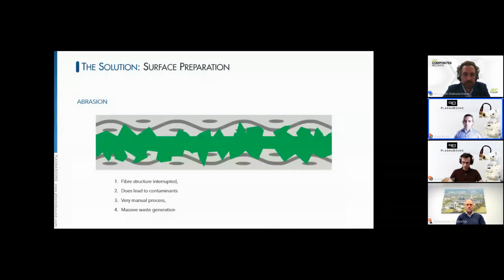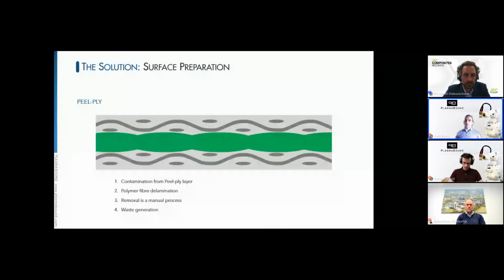Then finally, we have peel ply. It's very effective when done right, and many specialist adhesives are formulated to match it, specific sheet-based adhesives. However, contaminants from the peel ply layer and moisture ingress are not uncommon, particularly when using the nylon-based peel ply systems.